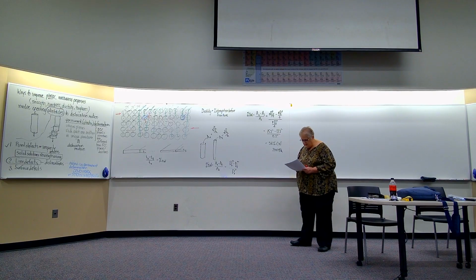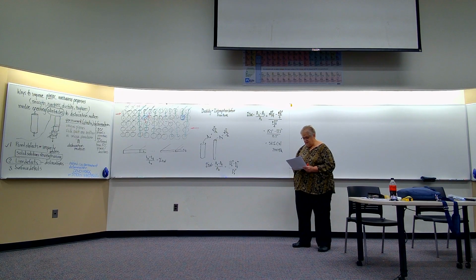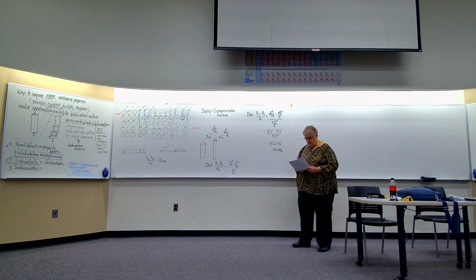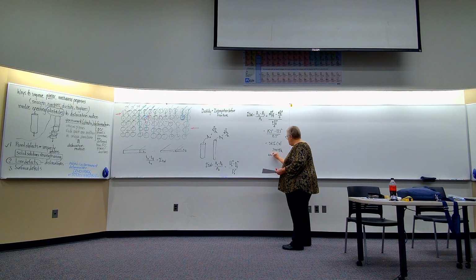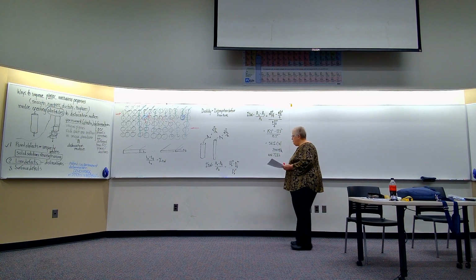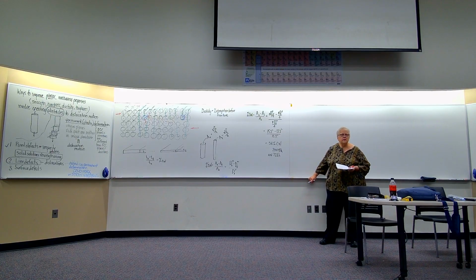And looking at that same point for copper, it looks like I'm maybe just under 10% ductility. Maybe more like 7. That's not good. I mean, that's about the bottom there.